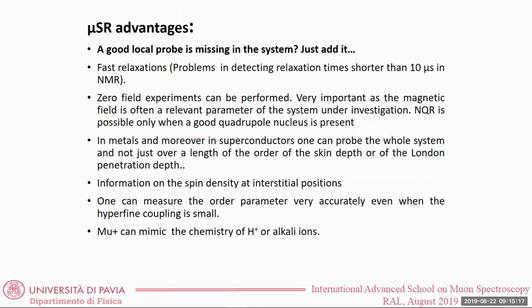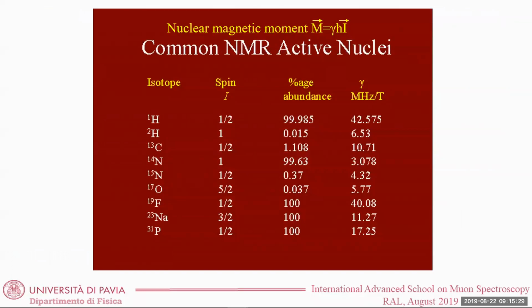The point is, for example, when you don't have a good local probe already inside your system. For example, you don't have a good nucleus. What is a good nucleus? Typically, a good nucleus means a nucleus which has a high natural abundance or a high magnetic moment, namely a high nuclear gyromagnetic ratio. For example, suppose you have a system with plenty of oxygen. You cannot study oxygen 16 because it's spin 0. You could think about using oxygen 17, but its natural abundance is very low, so very poor NMR signal, you cannot do NMR.